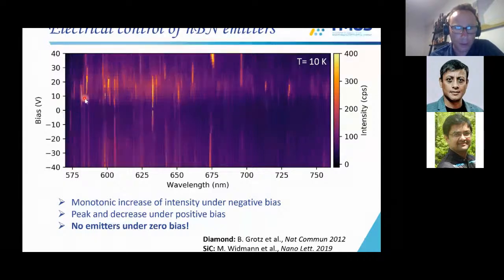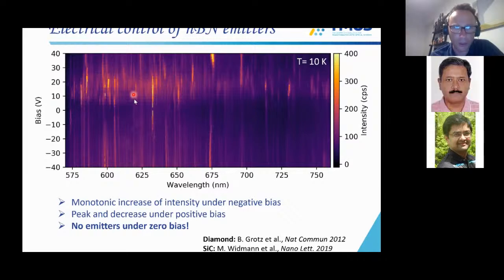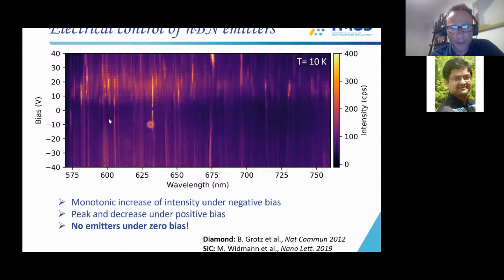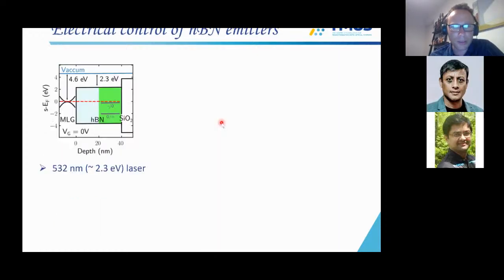So here is a good example. You'll see an emitter here turns on at 10 volts and then off again. And here it turns on and off again. And here on and off again. And on the negative bias, you have basically a monotonic increase. So you turn on and it slowly increases and never goes off. There were some similar works, again in diamond, a few years back that reported a similar effect, not exactly the same. And so we looked at it in a bit more detail and tried to come up with